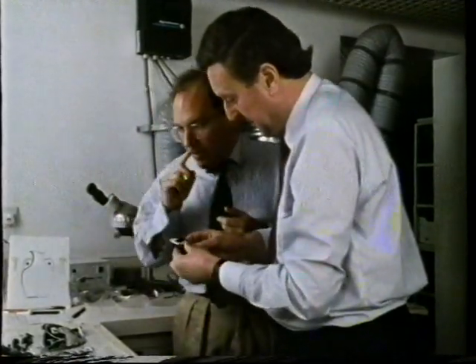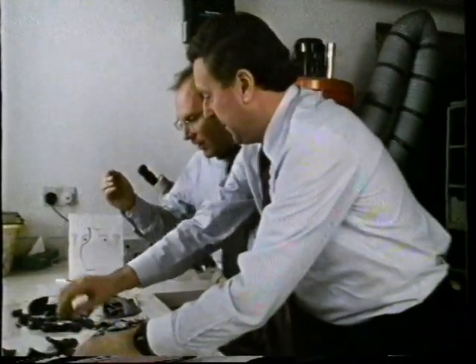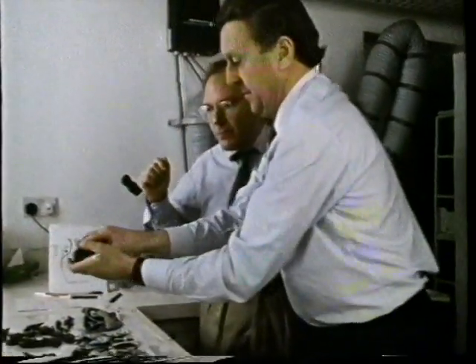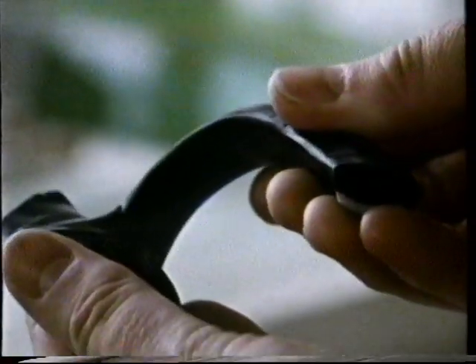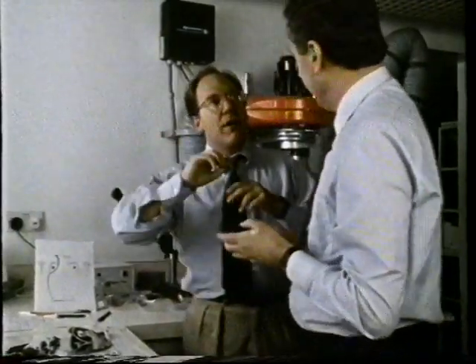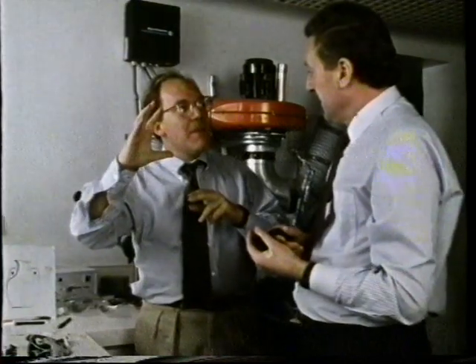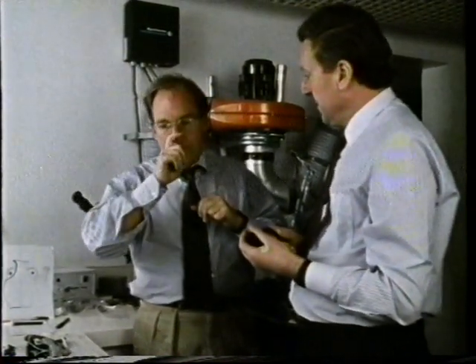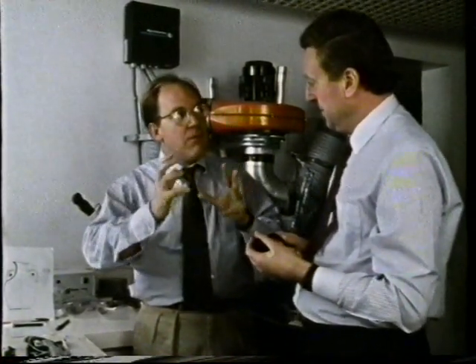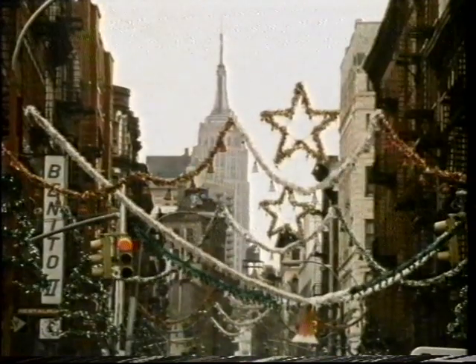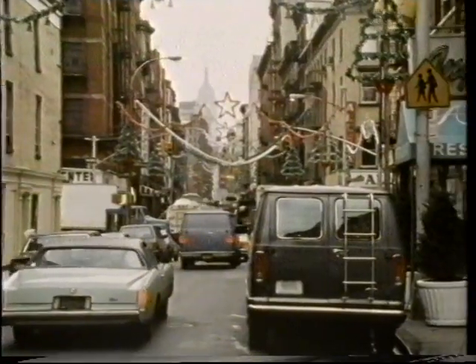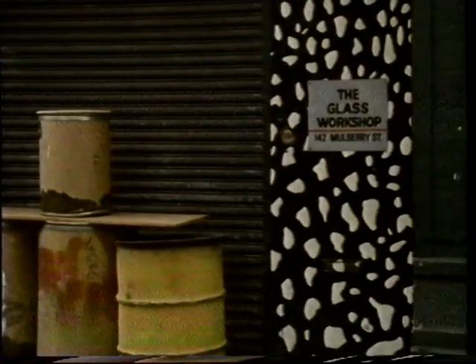Absolutely right. Now, if you look at the upper attachment point, this piece, you see that the handle was put down directly on the blue glass. So it may be the white only went up to so far, fairly near the neck. And that would have been that technique of dipping glass. I'd like to try that at the furnace. At the New York Glass Workshop, Bill Goodenough, with 25 years' experience, recreates a 2,000-year-old experience.